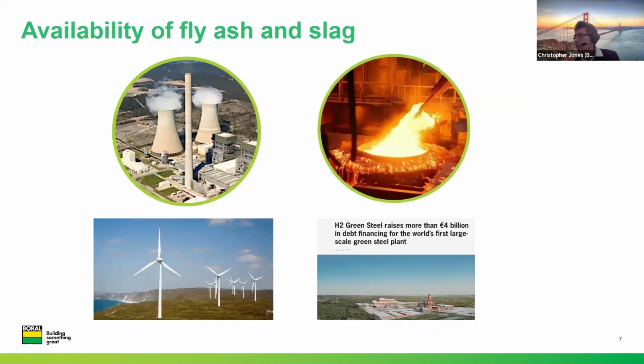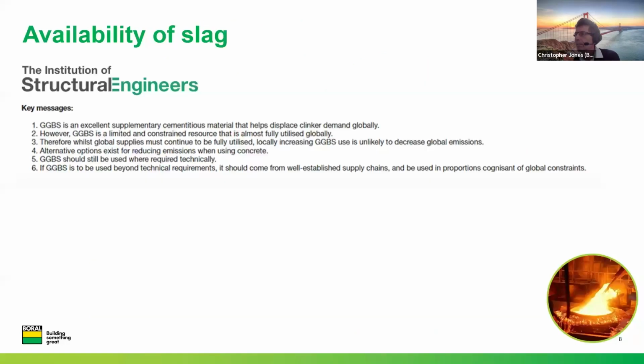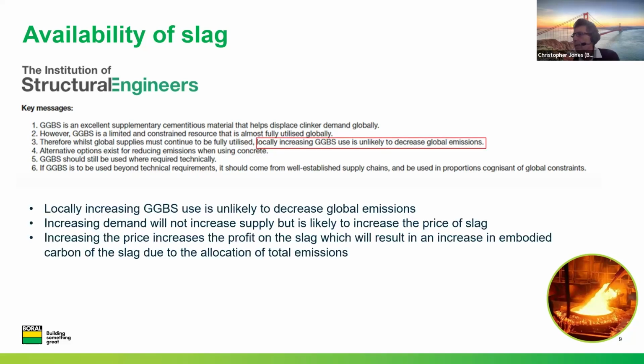So let's look at the availability of these two SCMs and the effect that renewable energy will have on the supply of fly ash and the use of electric arc furnaces will have on the availability of slag. Firstly, let's look at the current availability of slag. I thought this extract from the Institute of Structural Engineers webpage in the UK gave a good insight into this issue. It states that GGBS is an excellent SCM that helps displace clinker demand, which I think we already knew. But then it goes on to say that it is a limited and constrained resource that is almost fully utilized globally. And the key point is the one that I've highlighted.